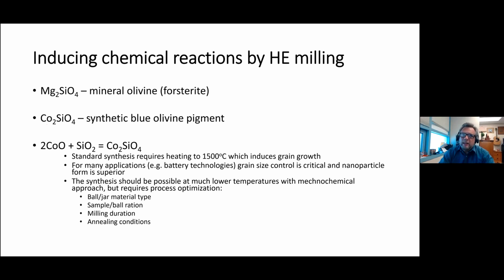So the ball milling approach seems like a good recipe to make nanocrystalline materials. All of the other methods that were developed successfully before required heating at high temperatures, as high as 1500 Celsius. These two attempts that we made at inducing polymorphic transitions without chemical reactions did not require heating. Just the dynamic shock provided enough energy to induce the transformations. So I thought maybe this would be a good way to synthesize cobalt olivine at ambient temperature.